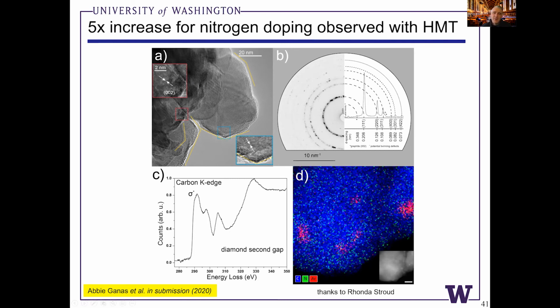But we've done a lot of electron diffraction with these materials as well. We can see some graphitic domains. This inset shows the 002 peak of graphite. So there's some turbostratic graphitic domains that are also forming in this experiment. But we can clearly index these peaks to cubic nanocrystalline diamond.